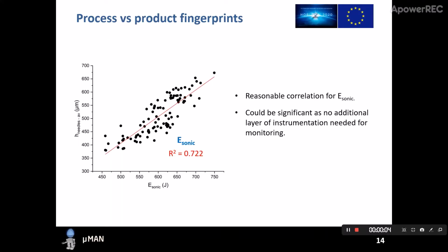Another significant result from our experiments was the correlation between the sonication energy and our microneedle height from each part, and we have seen R² values of approximately 0.7 for sonication energy that is taken from the machine. And this could be quite significant because monitoring this process fingerprint needs no additional layer of instrumentation for inline monitoring, no thermal cameras or pressure transducers or any additional equipment or apparatus. So this sonication energy fingerprint could be a useful and cost-effective method for predicting or doing inline quality inspection of the microneedles, and this could be considered a good result.